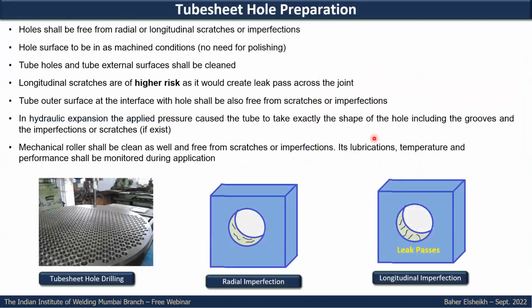For the preparation, the tube sheet hole shall be clean, and there is no specific requirement for a polished, well machined hole, because somehow you need to have a force to grab the tube to the tube sheet hole. But it's very important to avoid any scratches or imperfections in the tubes. As a general rule, they should not be there, but we also need to understand that a longitudinal imperfection is considered higher risk compared to a radial imperfection. Now, if this is the shell side and the other one is the tube side, with a longitudinal imperfection you will have a leak path between the two sides. The radial one is still not a leak path, so you can have some tolerance for radial imperfection. But generally, you should not have any imperfections or scratches in the tube sheet hole.